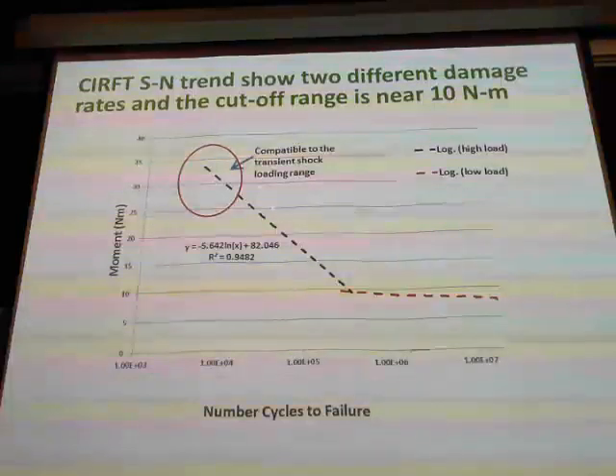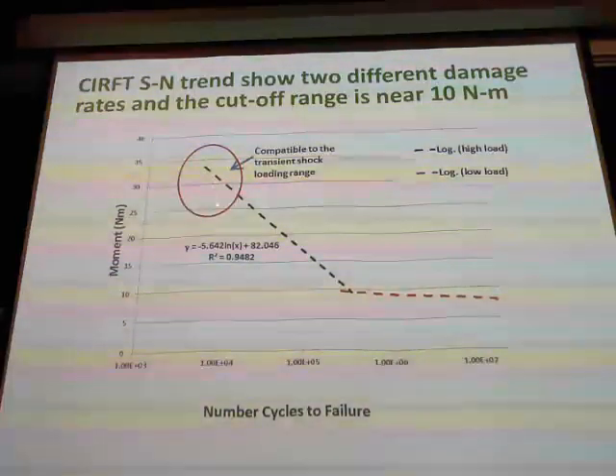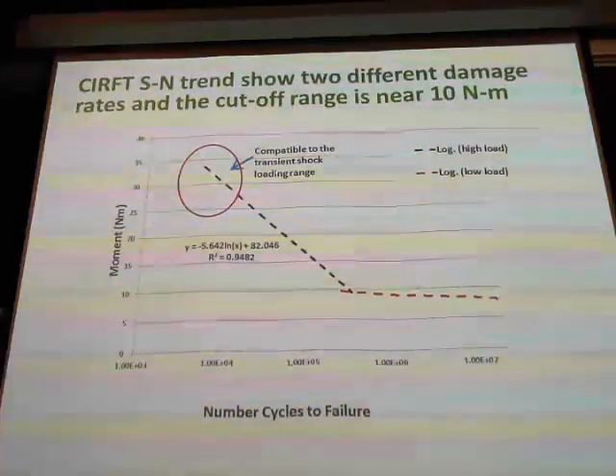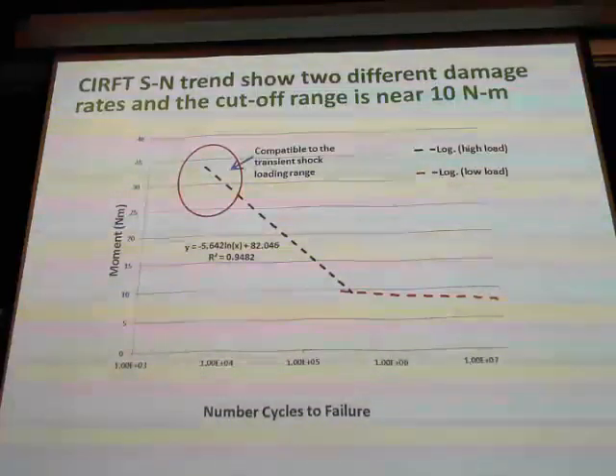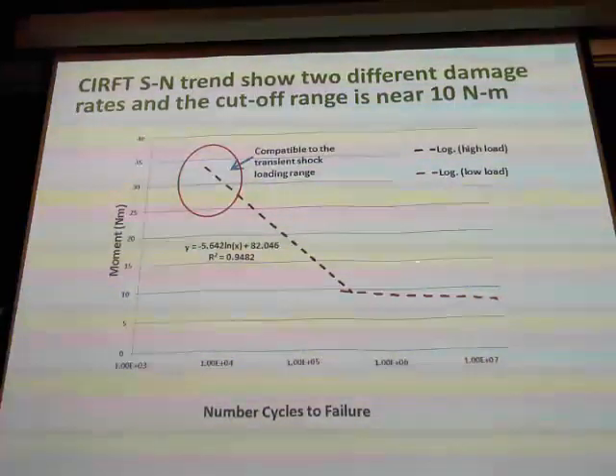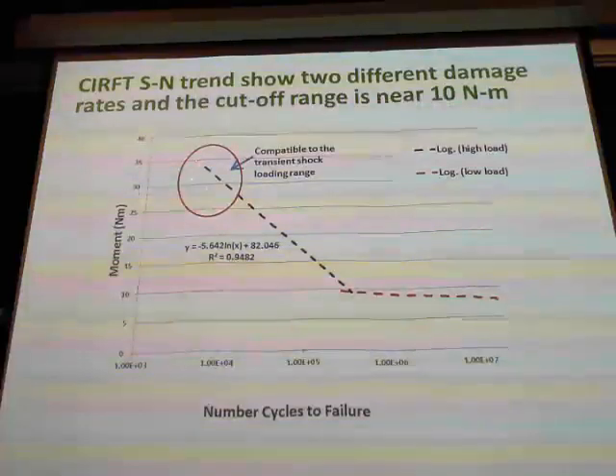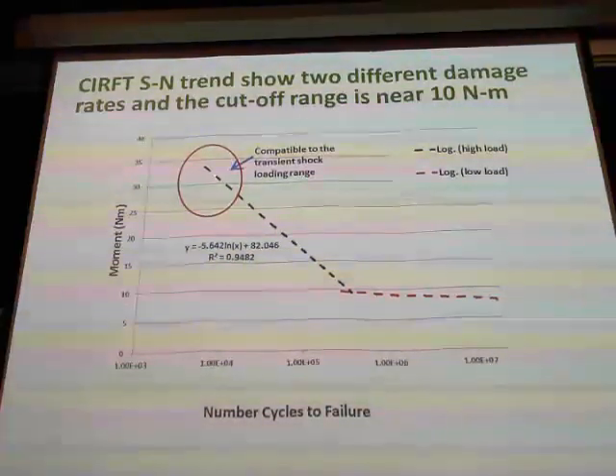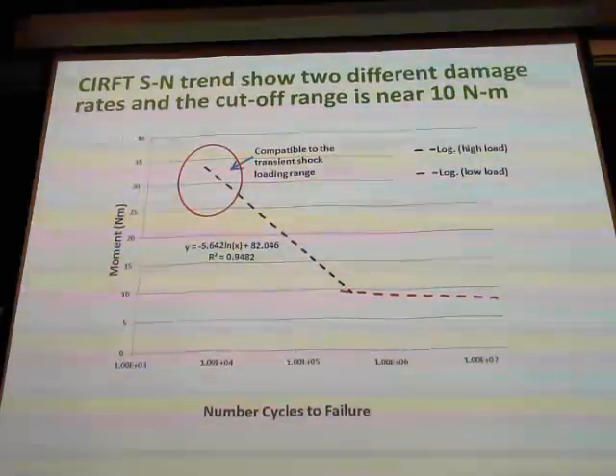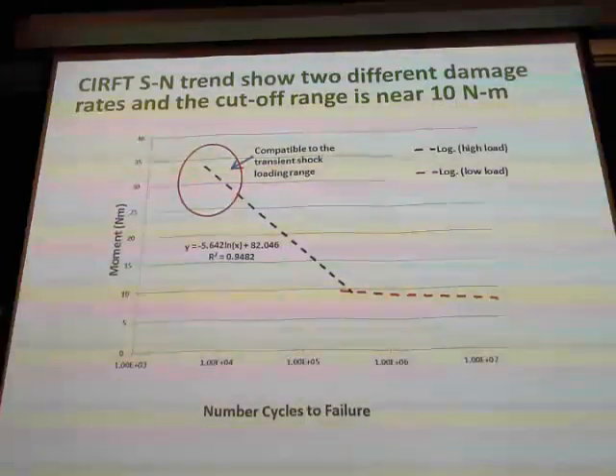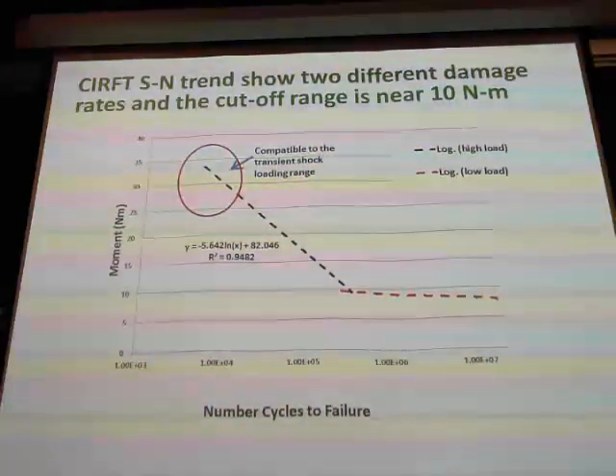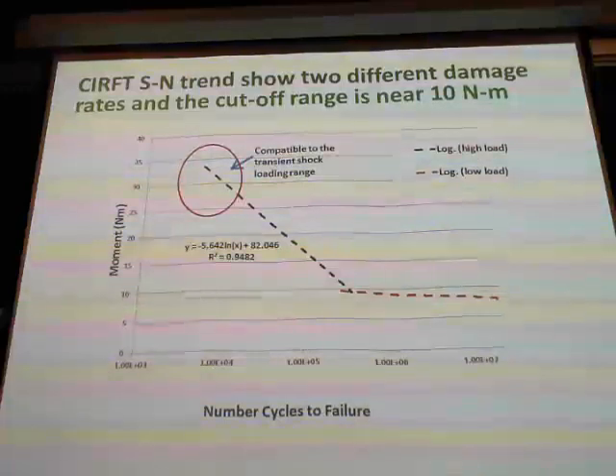So at this region, a transient shock can push to this area. So in our S-N curve, we can have the endurance limit here. We also can project to high, because at a higher loading rate, you have a much shorter lifetime. So combined loading is very critical. This is our next critical step.